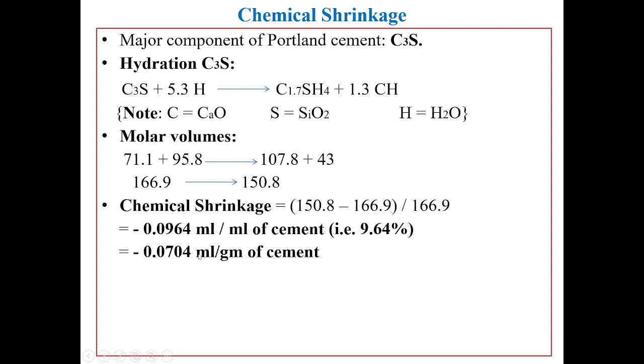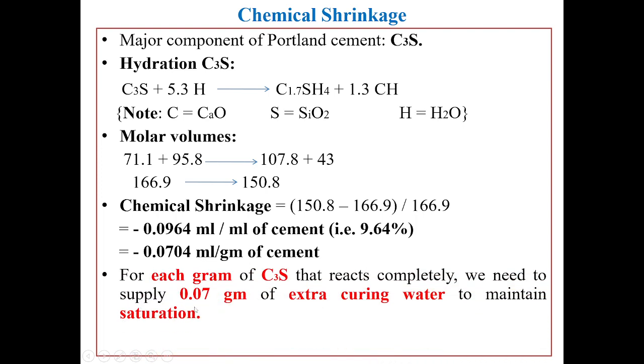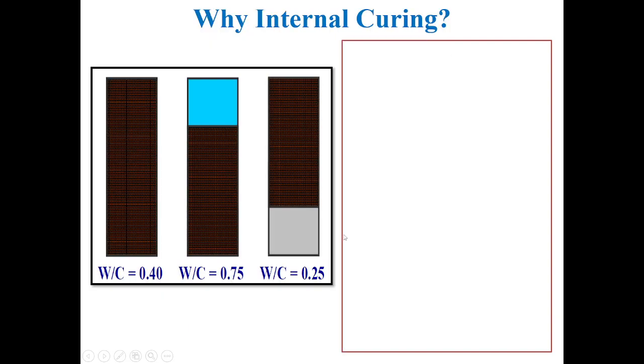So when I convert that into ml per gram of cement, because we know that approximately 50 kg of cement weighs 35 liters, 34 to 35 liters, it becomes minus 0.0704 ml per gram of cement. So this clearly shows that for each gram of C3S that reacts completely during the cement hydration, we need to supply 0.07 gram of extra curing water so that the saturation is maintained. That is why the chemical shrinkage is the main thing, because of which we have to go for internal curing.